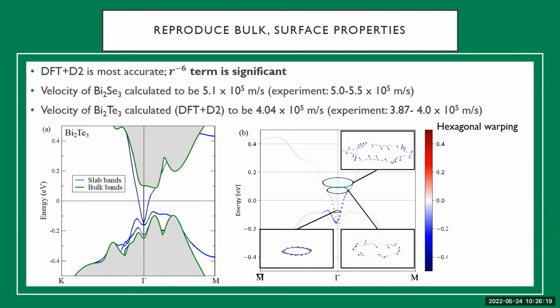So in the figure on the left, I show the topological surface states of bismuth telluride in blue. And the part near where these two blue bands cross is called the Dirac point. And the velocity is the slope of that state. I mean, the Dirac velocity is the slope of that state close to the Dirac point. And in the figure on the right, I show the same states, but I've plotted their spin texture.